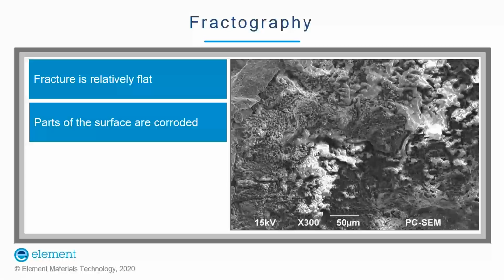Fracture morphology observed under SEM is presented in this slide. As shown in this slide, the fracture surface appeared to be flat and brittle in nature, as we've seen before. Parts of the fracture surface appear to be corroded. Corrosion product was observed on the fracture surface even after extensive cleaning.